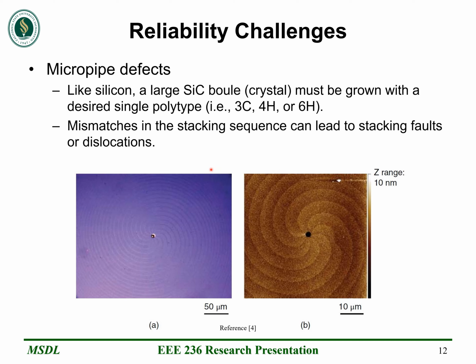On the left side is just a regular photograph through a microscope, and on the right is a photograph using atomic force microscopy. An atomic force microscope consists of a very tiny needle that scans across the surface of the silicon carbide wafer, and that needle will move up and down as it comes in contact with different heights in the topology. And what you end up with is essentially a map of the topology of the surface. And as you can see, these stacking faults have caused this cyclone or spiral shape on top of the wafer that ultimately end in a killer defect or a micropipe defect. A micropipe defect is essentially a giant hole in the silicon carbide wafer where the mismatches converge. So as you can see, this is one of the major defects that manufacturers are facing while trying to fabricate silicon carbide transistors.